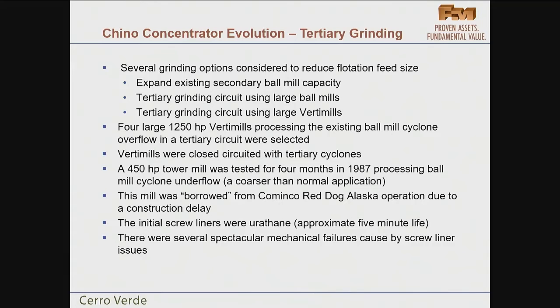It was very interesting. The bill arrived. We took a look at the screw, and the screw had urethane liners on it, which we think the wear life was around 5 minutes. There were several spectacular mechanical failures because the liner comes off, it pushes the shaft over and breaks the shaft. Then we converted to steel liners, and the liner comes off, same thing happens.